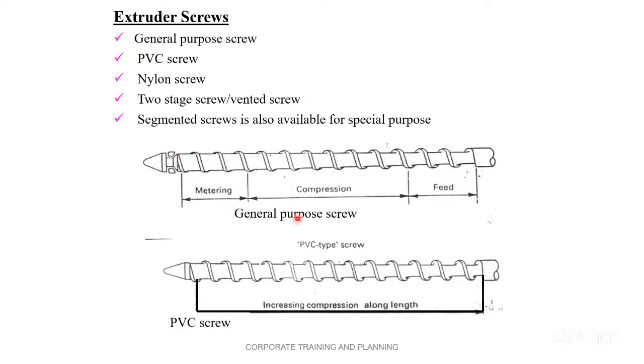Now, friend, see here: feed zone lower, see the compression zone constantly increases here, see the metering zone, constant diameter. Here is also constant root diameter. Here, root diameter goes on increasing. See, very long. Why this? The material should get plasticized. That's why in compression, the material gets compacted and the granules convert into liquid polymer. And then it will be pushed to the metering zone.